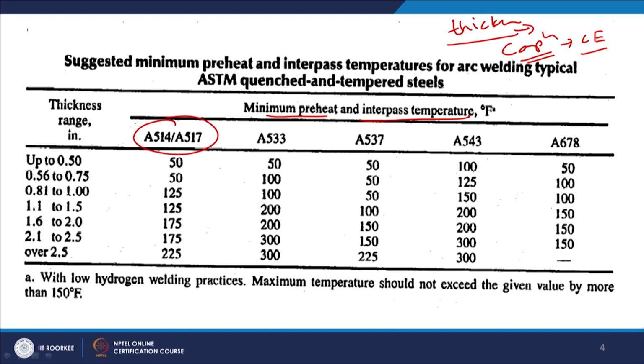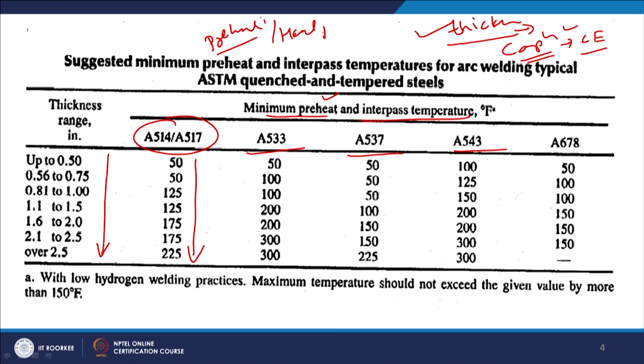Like say the most common series of the Q&T steel is A514 and A517. And we can notice that with the increase in thickness of the plate to be welded, there is a continuous increase in the temperature to be used for the preheat, and likewise for the different steels there are different values of the minimum preheat temperature, which means these preheat temperatures need to be established in light of the application for a given thickness and for a given type of steel, so that the preheat temperature and the heat input combination offer us the required cooling rate, so that we have the desired set of microstructural features to obtain the required combination of mechanical properties in terms of the yield strength and the toughness or the notch toughness.